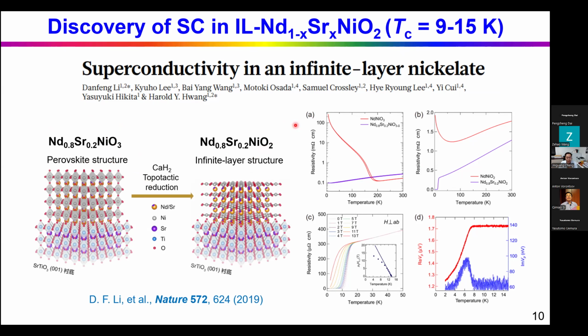For this infinite-layer phase, the resistivity measurement and the AC susceptibility show the superconducting transition with TC around 10 Kelvin, the onset around 15 Kelvin, and zero resistivity around 9 Kelvin. So both the zero resistivity and the Meissner effect confirmed that this is bulk superconductivity in the nickelate. This experimental breakthrough is really exciting because this proposal was made 20 years ago, and finally the nickelate superconductor was discovered in experiment.